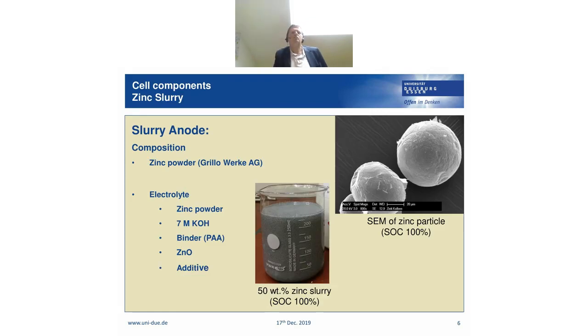So here we see what our slurry looks like. The main ingredient is of course the zinc powder. We obtain the zinc powder here from a company in Duisburg also. It's Grillo Werke, they are called, and they are one of the leading zinc producers, also for primary zinc air batteries. The particles have a diameter of around 50 to 70 microns. In this SEM photo, they are perfectly spherical, but other forms can be produced, and we also tested them electrochemically.